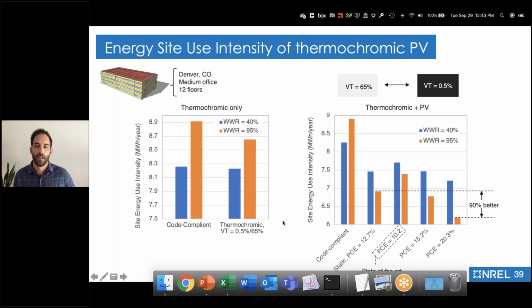So now the magical thing happens, let's say magical. On the right side here, we show site energy use intensity as a function of different photovoltaic thermochromics. We're doing this in reference to the code compliance of the low-E window, and the static PV window, which is the second stack here. This is actually what I call generation 3, or the organic photovoltaic selective absorber at 12%. So this is at that high power conversion efficiency rating. And now we compare these 3 sets of data on the right, where we have switchability. So now we're going between a transparent state of 65% and a visible transmission in the dark state of 0.5%. So that's like a privacy setting on a dynamic glass.